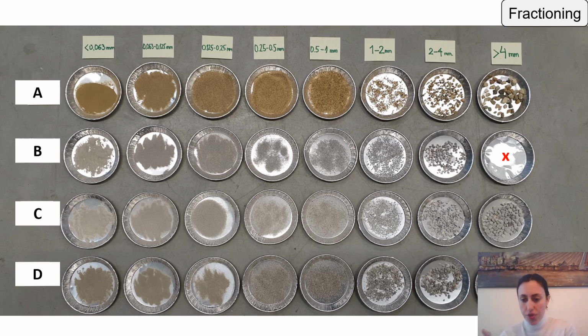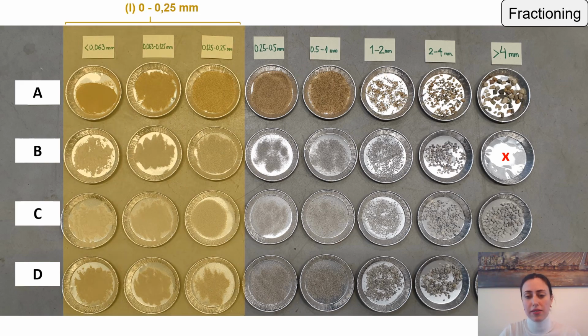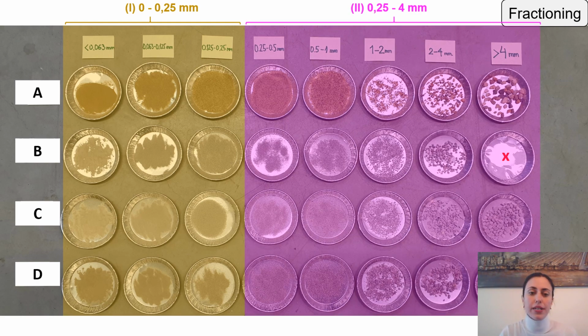So we have three sources of recycled material, and A is a river sand. You can already see by the color the first row of the materials, and different fractions of these materials. Since it's very hard to characterize each of these fractions, I have decided to merge these fractions into two and start the characterization from them, 0.25 to 2 and 2 to 4, and compare their properties to the total fraction 0 to 2 millimeter.